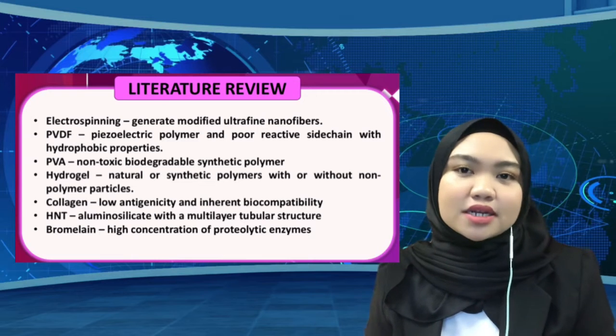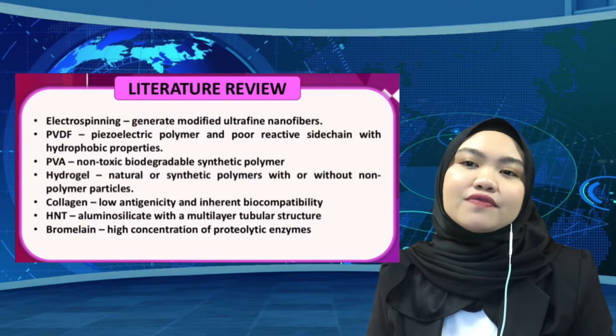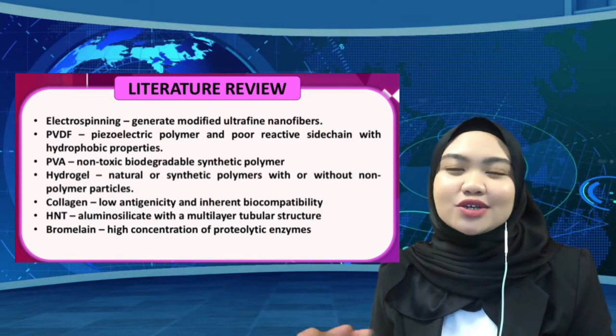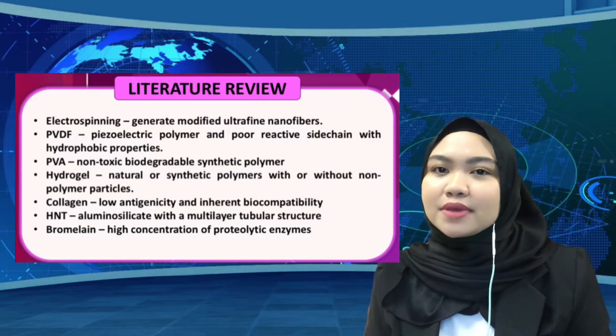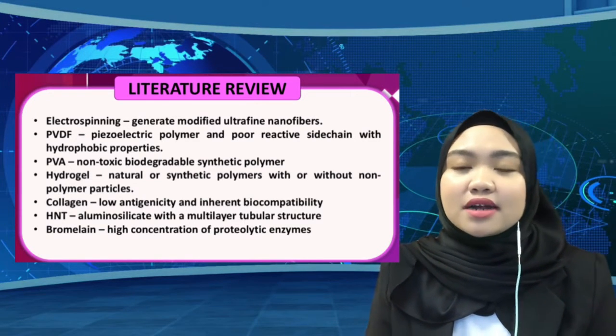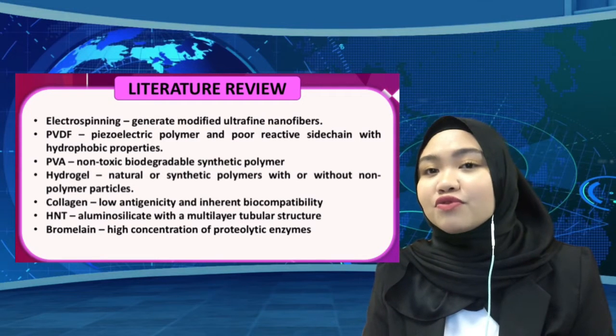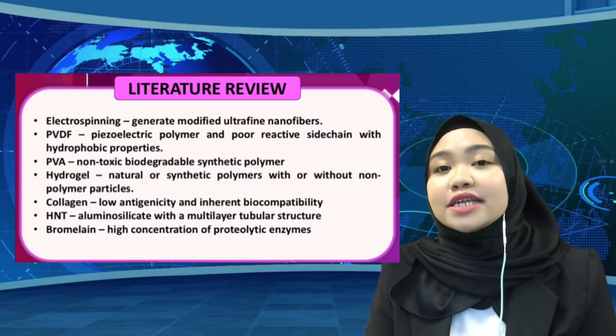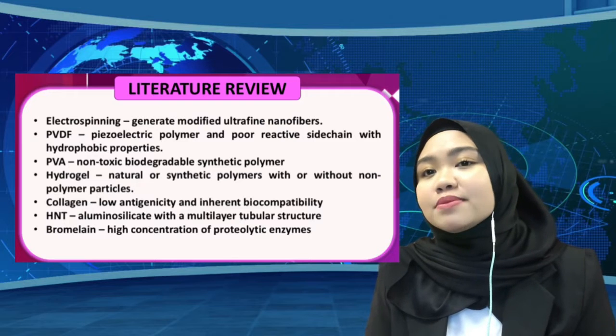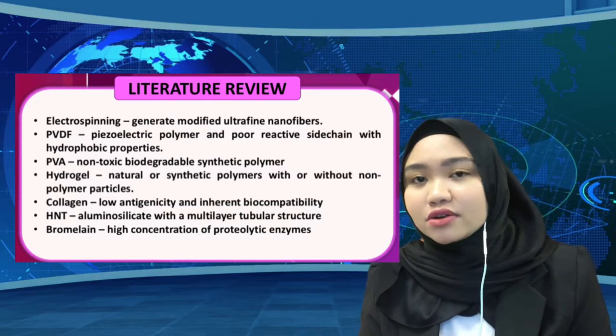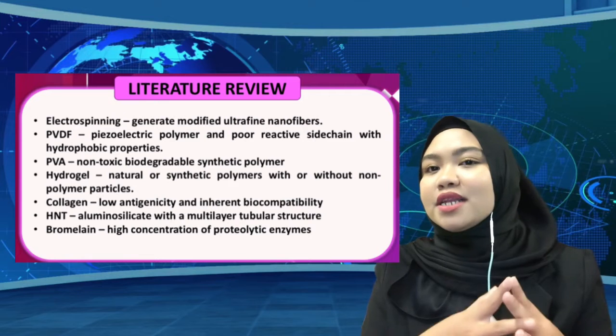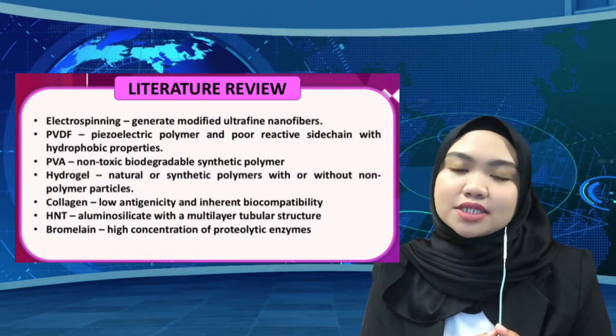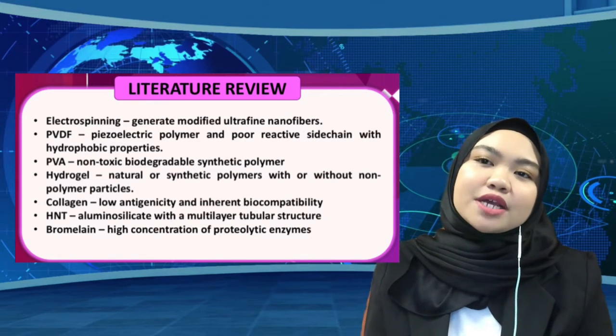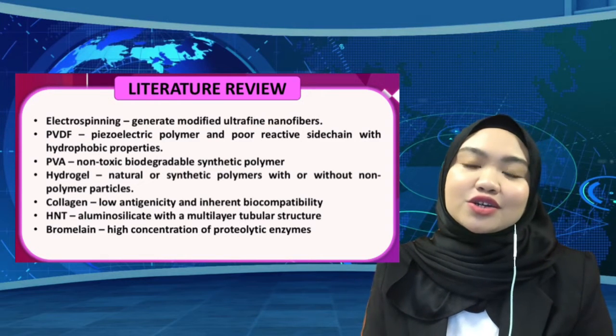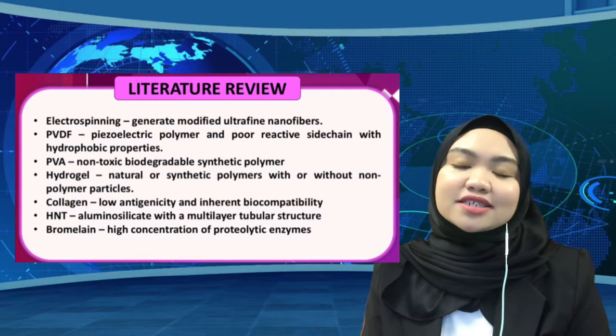So for Bromelain, Bromelain is a pineapple extract found in all sections, which has a high concentration of proteolytic enzyme. Bromelain, which acts like a drug in the electrospun, is proven to remove burn debris as well as speed up the healing process. So Bromelain has been chosen as the enzyme in the composite for drug loading testing. The concentration of Bromelain in this testing is 200 mg and 400 mg respectively. From the experiment, it can be observed that the low concentration of Bromelain has a potency of high drug loading. So next we go to the methodology.